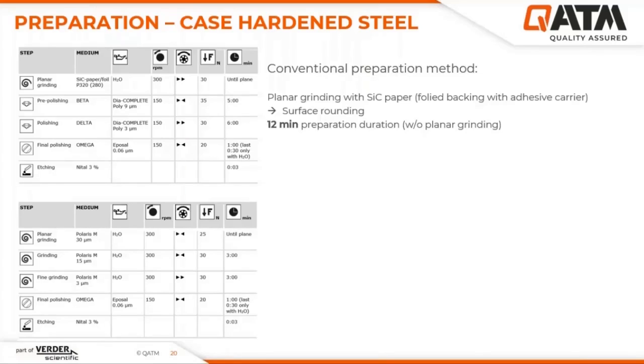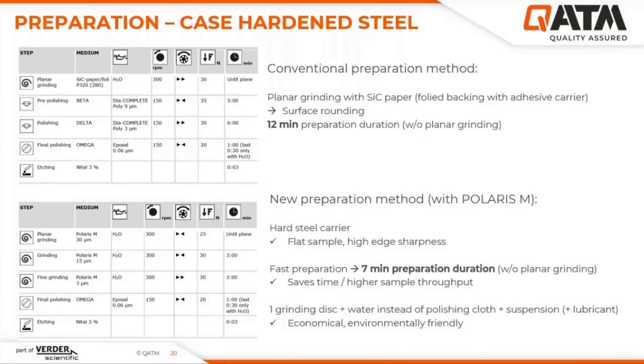In summary, there are several advantages with the new preparation method. In addition to the good flatness, the preparation time is shorter. We need 7 minutes in total instead of 12 minutes, so the sample throughput can be increased within the same time, and fewer consumables are required by replacing the 2 diamond polishing steps with grinding steps. Also, replacing the paper produces less waste in the long run. It is also more cost effective.